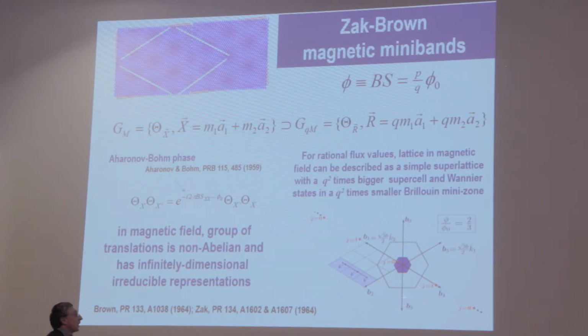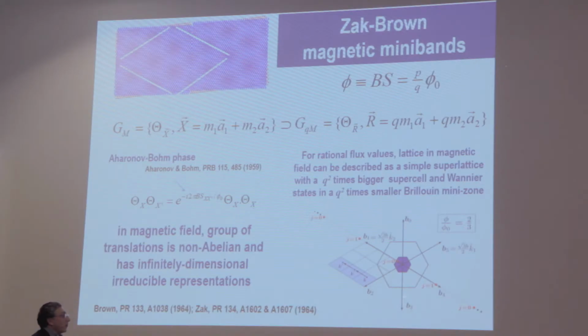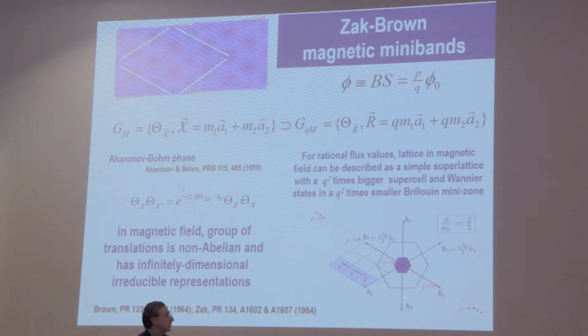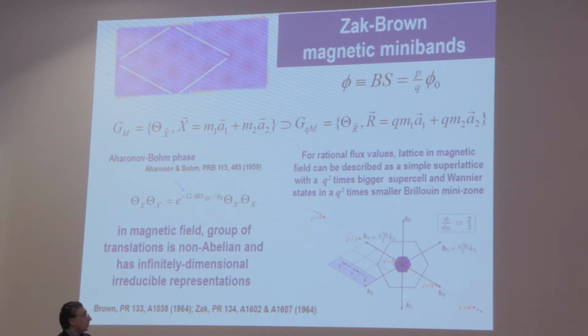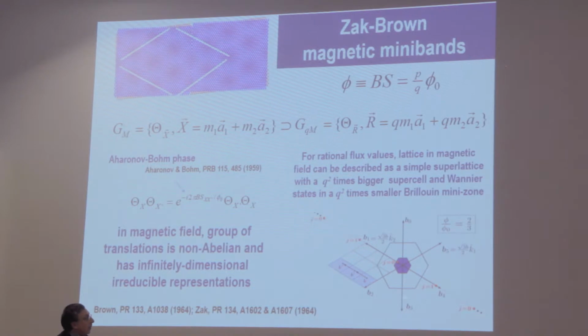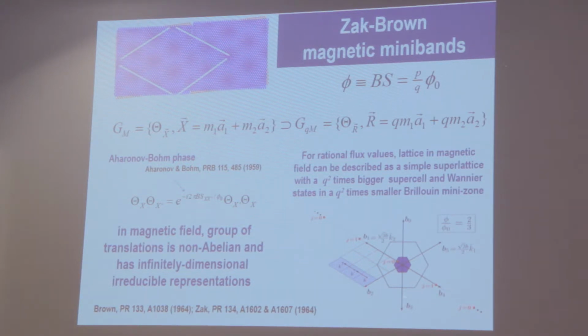And in this case, the Aharonov-Bohm phases will be equal to 1, and you get back the subgroup of this abelian group, of non-abelian group, which in terms of translations becomes abelian. And that means that for this larger size of the supercell, you can use all the same description of electronic states in terms of the plane waves, in terms of the Wannier states, but in a smaller mini Brillouin zone corresponding to a larger period of the superlattice that we had to choose to provide the integer number of flux quanta piercing this larger supercell in the description.